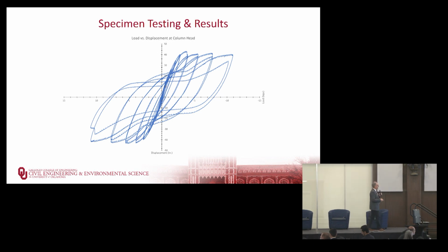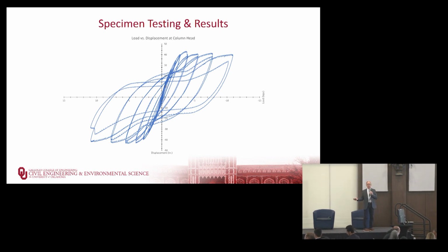But the interesting thing is the column still has a lot of post-buckling capacity. And what happens is you start to see this dip and then an increase in load. This is because when you're pushing in one direction, the part that's in compression, the steel tube buckles. When you pull it back and start pushing in the other direction, you straighten out that buckle, and then the steel tube starts to take more and more tension. So you get this very, very interesting behavior.